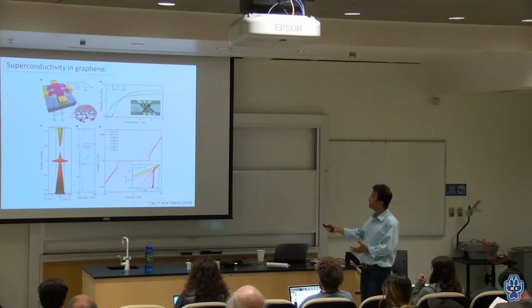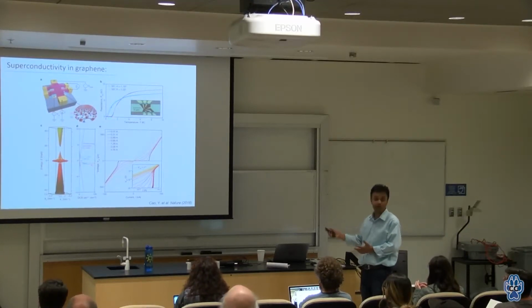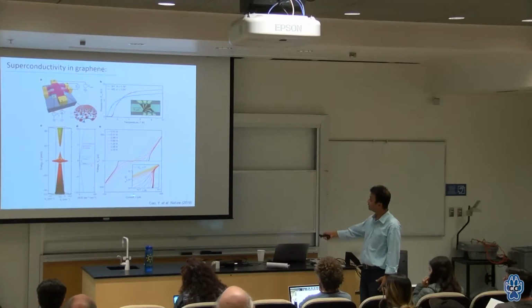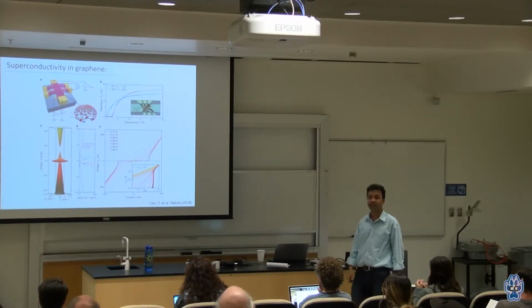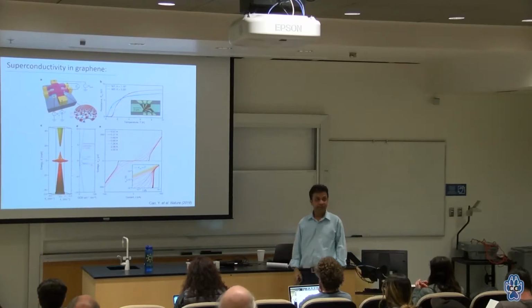So you can see that at theta of 1.5 degree, when you go to low temperatures, boom, you go to superconductivity. And this is your current data as a function of voltage. You can see all this superconducting behavior, right?